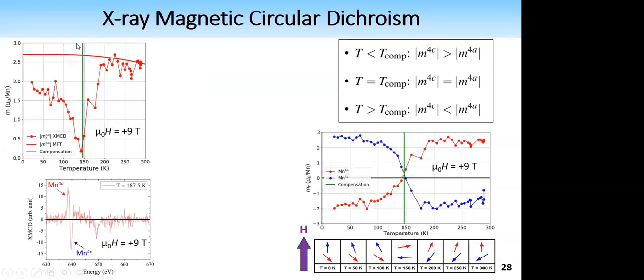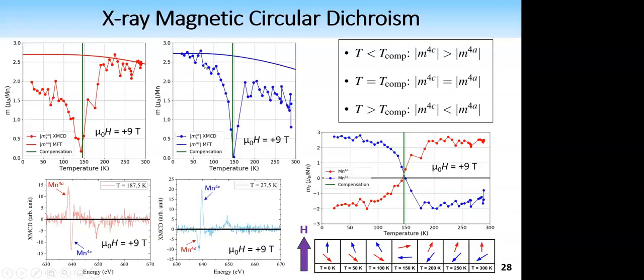From MFT, I've calculated the temperature dependence of the 4A and 4C sublattices. Here I'm showing the MFT data with the solid line. I was able to scale it to the value at high temperatures using the assumption that the 4A moment, away from compensation in a 9 Tesla field, is fully aligned with the field along the Z-axis. So we're getting the full Z projection of the moment. And for 4C, it was the opposite temperature. At lower temperatures, I assumed the 4C sublattice is perfectly aligned with the Z-axis. And therefore, we were able to obtain this data.